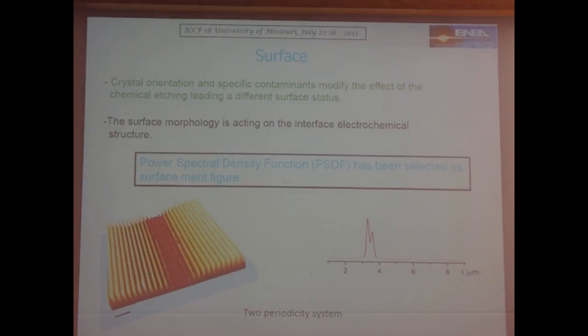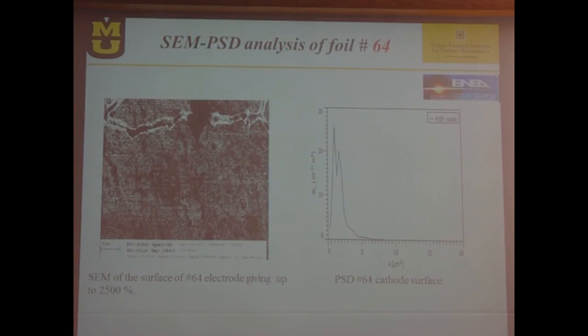But we looked for some kind of figure of merit in order to identify or quantify the quality of the surface, the morphology of the surface. So we have selected the power spectral density function, which is basically a scanning of the surface with atomic force microscopy, and then analyzing it with Fourier transform analysis, to come up with figures of merit which give us some quantitative results on the morphology of the surface. We had an intuition that the morphology is important, and I think we were right.